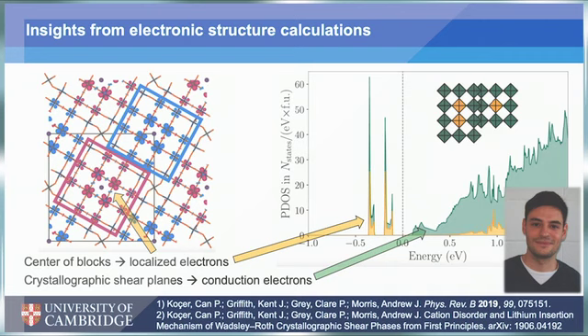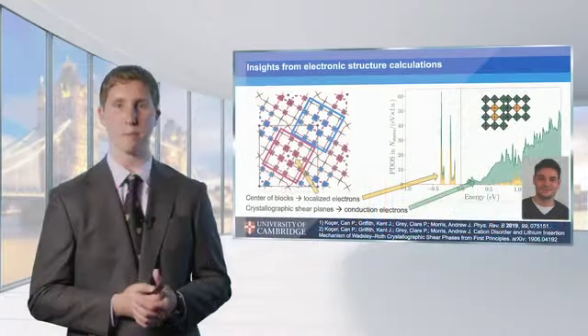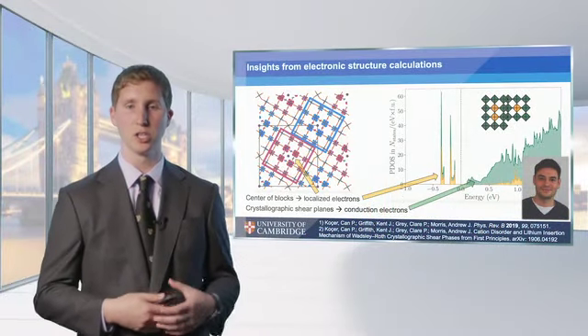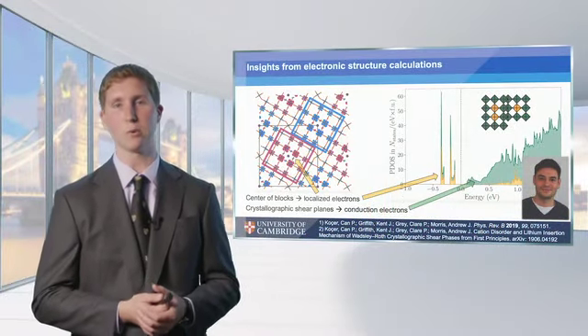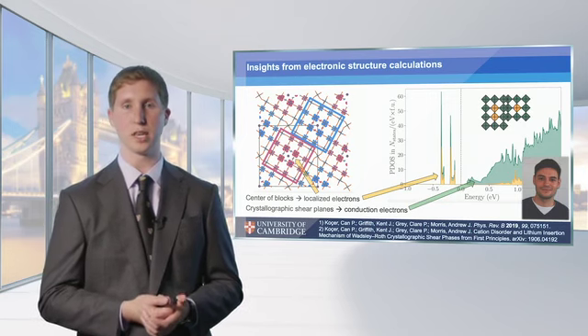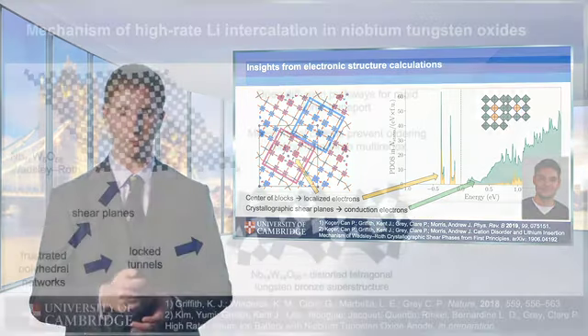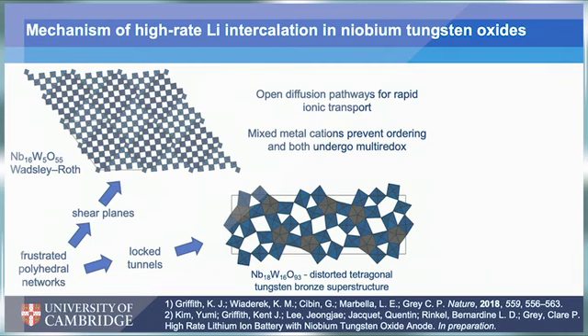And so these crystallographic shear planes that run orthogonal to each other actually provide a totally interconnected electronic conduction pathway that goes along with our rapid lithium ion conduction. So putting these 2 things together provides exactly what we'd need for high rate lithiation of an electrode active material. So if we take all of this together, we're really starting to get an understanding of what the mechanism is of this high rate lithium intercalation leading to rapid energy storage in the niobium tungsten oxides.